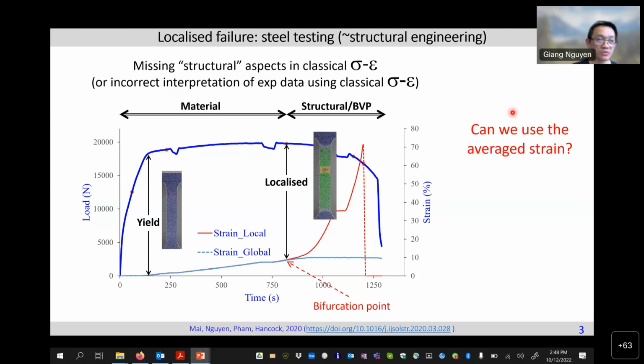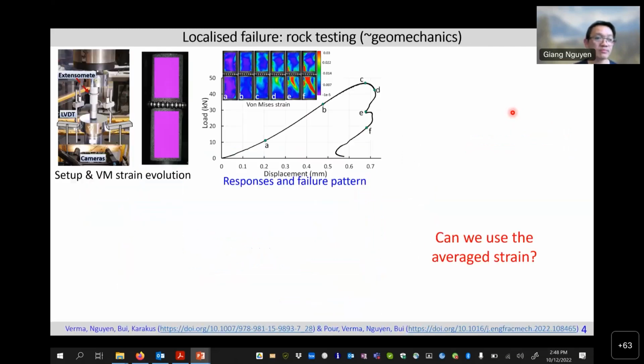Okay, it becomes a structural or boundary value problem. We do the same thing if we run tests for geomechanics, rock in this case. We do this, we record it, we plot the strain. You can see the strain evolution and intensive deformation strain here, very high in a zone that in the end leads to cracking, failure of the specimen.